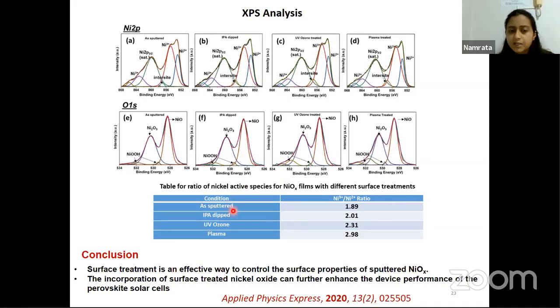So when we have the as-sputtered nickel oxide, the Ni3+ to Ni2+ ratio is the lowest, and with plasma we have the highest. And this explains why we have the highest performance for the plasma treated nickel oxide.